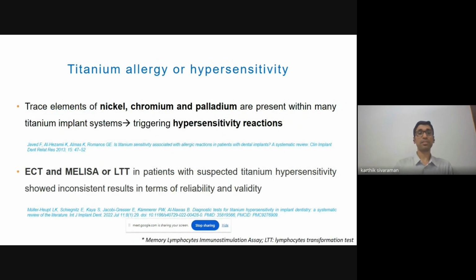There are studies which have hypothesized that the trace elements of nickel, chromium, and palladium, which are present in these titanium alloys, might in fact be responsible for the documented titanium sensitivity, hypersensitivity, or allergy. And it's not per se the titanium as such. Also, there are diagnostic tests which are frequently discussed, including patch test, ECT, MELISA, or LTT. There are studies which have concluded that these have shown inconsistent results in terms of reliability and validity.